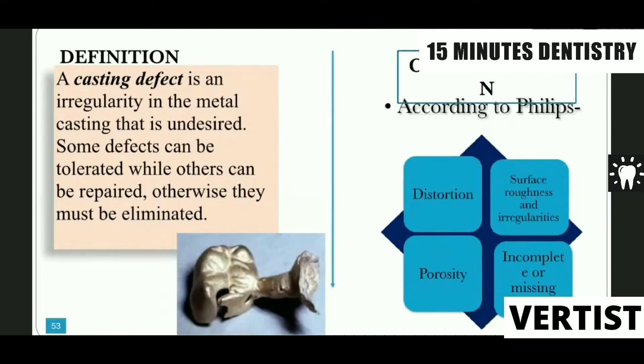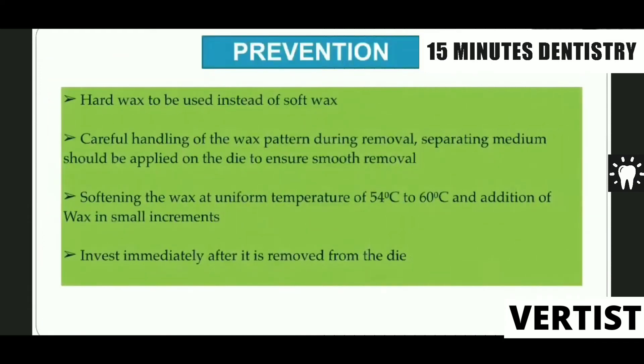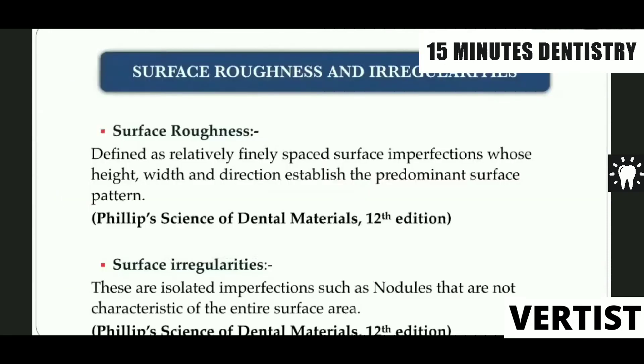The defects that occur are distortion, porosity, and incomplete castings. Distortion can be due to mold expansion and due to the wax pattern distortion. The different reasons are highlighted in the box on screen. To prevent distortion, you can use hard wax, careful handling of the wax pattern during removal, separation applied to the die for smooth removal, softening the wax at uniform temperature, and investing immediately after removal from the die.